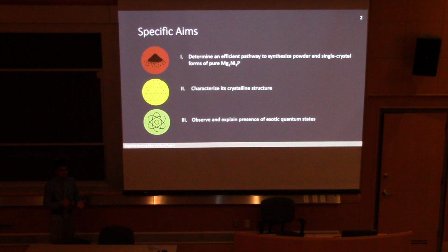Additionally, we want to try and form single crystal forms because if you have a polycrystalline material, where you take a bunch of crystals and they're just stuck together in different orientations, you have a lot of confounding variables, which makes it difficult to do any sort of measurements. However, having a single crystal form has only one single crystallographic orientation by which we can measure intrinsic properties of said material. We then want to characterize this crystalline structure, determine whether or not it actually conforms to what we predict the material to be, and then finally observe and explain the presence of exotic quantum states, as I mentioned earlier.